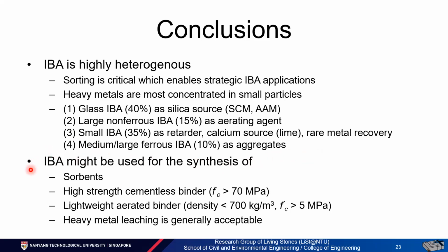Throughout this presentation, we demonstrate that IBA can also be used for the synthesis of sorbents, the high strength cementless binder purely using glass, and also the lightweight aerated binder with a density less than 700 kg per cubic meter and a compressive strength more than 5 MPa. And the heavy metal leaching is generally acceptable.